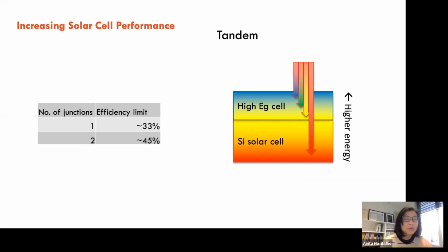So how do we increase the solar cell performance? One way to do it is to stack cells. So you can stack a higher bandgap cell on top of the silicon. So the high bandgap cell may be responsible for absorbing light from red all the way to UV, 2 eV or above, for example, and therefore it gets less hot and becomes more efficient. So as soon as we increase the number of junctions from 1 to 2, so we call it multi-junction tandem, the efficiency improves to 45%, and that's the theoretical limit.